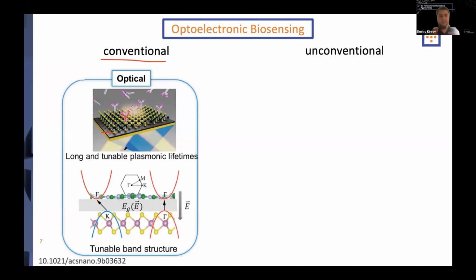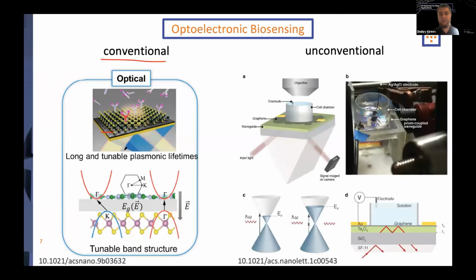And you would shine a light through the prism. You would induce plasmonic resonance on the surface. And this plasmonic resonance is very sensitive to anything happening on the surface. So whenever a molecule reacts with your recognition elements, your resonance shifts, and you can create a really sensitive biosensor.